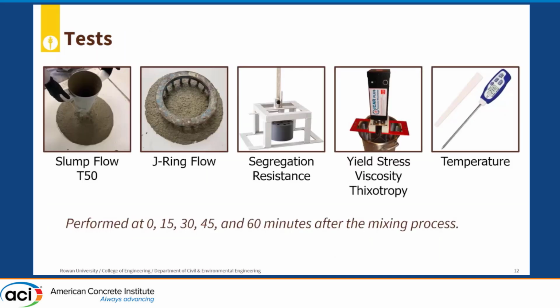Here are the key tests that we've done for the project. We have the slump flow test and the J-ring flow test. The slump flow test is for workability, and the J-ring flow test, when compared to the slump flow test, will give you the passing ability. We have the T50, which is the time it takes for the spread diameter to reach 20 inches or 50 centimeters.